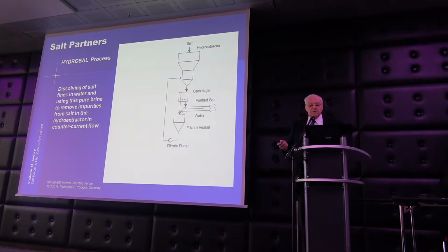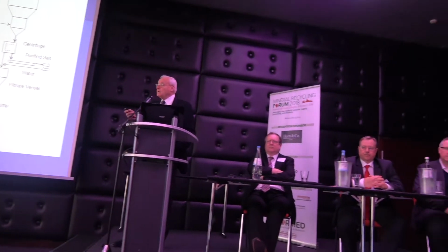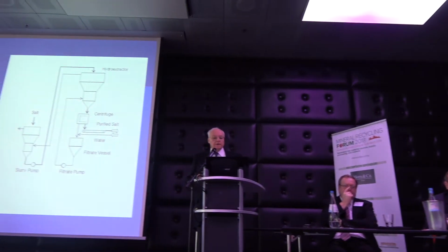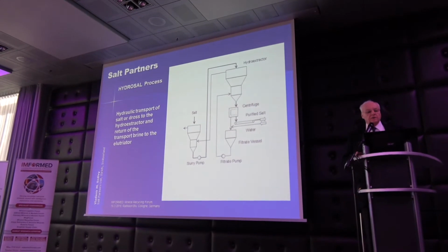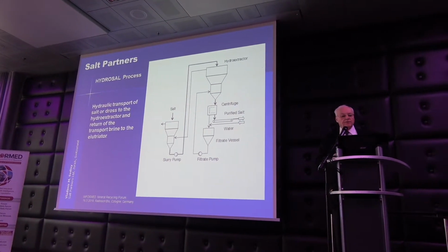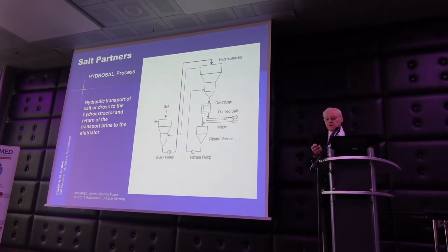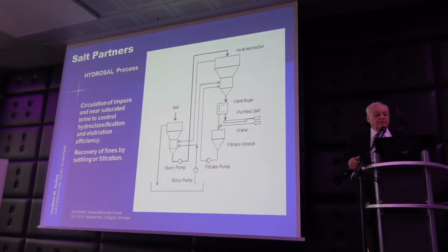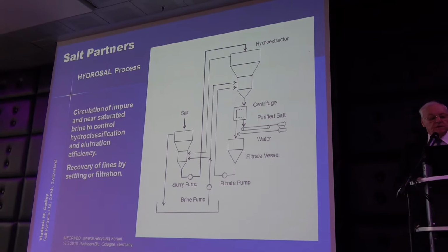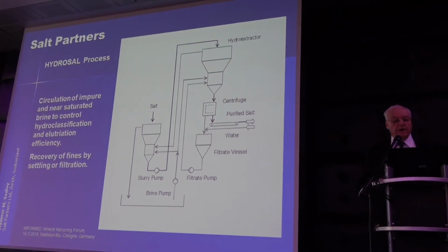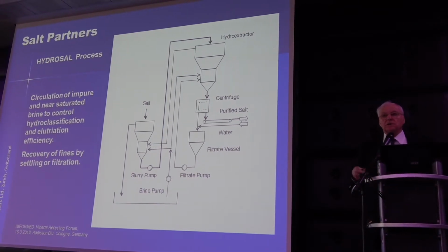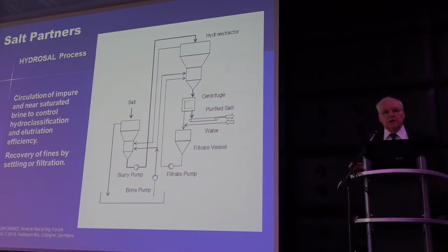The leaching actually takes place only in this lower part of the hydro extractor here. That's where the countercurrent flow of the solids against the flow of the solution upwards takes place. Then, of course, we have to get the material to the hydro extractor. This is what we do with hydraulic transport. We mix the salt with the overflowing brine and pump it to the top of the hydro extractor. And then to close the loop, the overflow from the elutriator flows to a settling pond, from where we pump the brine back to the hydro extractor and to the elutriator to adjust the countercurrent flow the way that we require it.